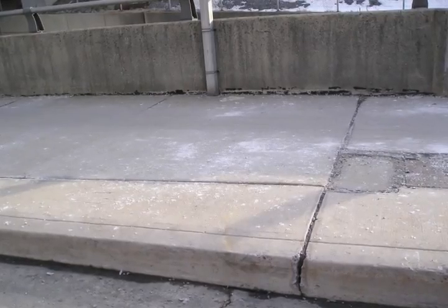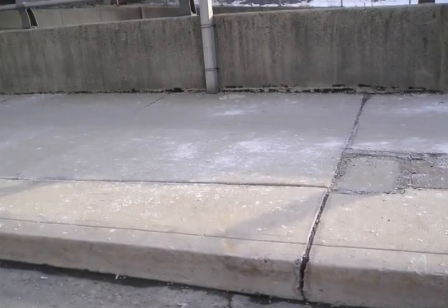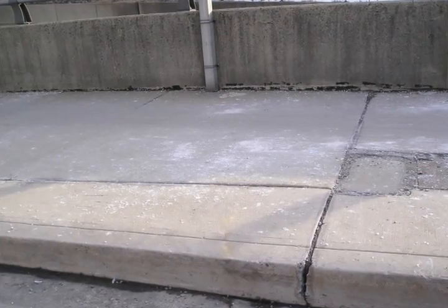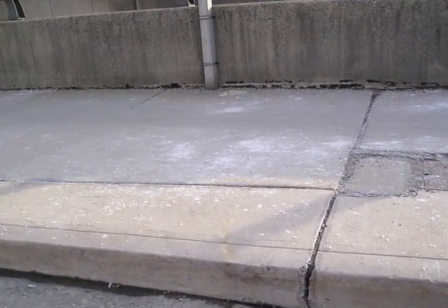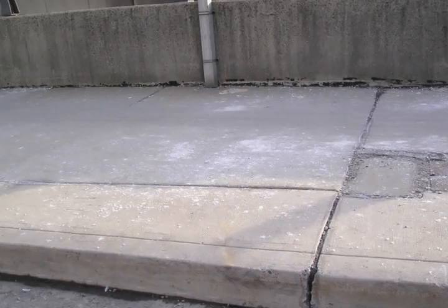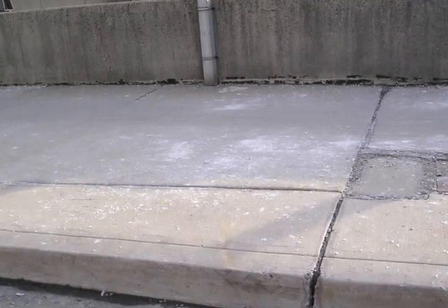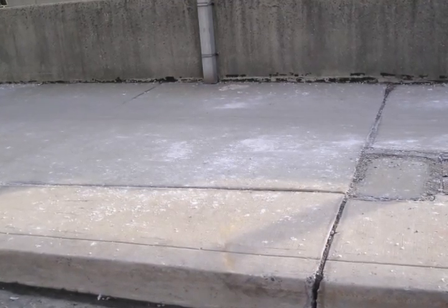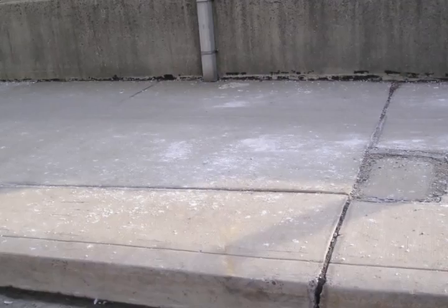Here's a picture of the salt that's accumulated on a bridge in New York. And to give you some idea about our application rates in Utah, we apply about 250 pounds of salt per lane mile with each de-icing event. So to put this in perspective, to treat the entire length of University Avenue here in Provo and Orem, we would need 15,000 pounds of de-icing salt with each event.